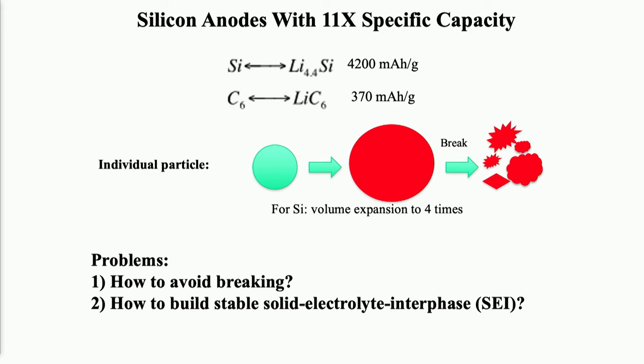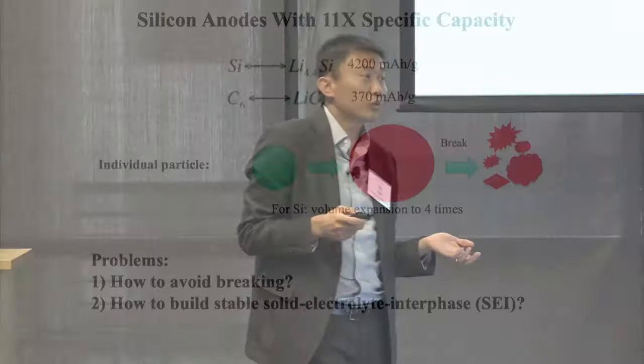Silicon stores a lot more lithium, but its volume expansion is gigantic. It's about four times once lithium is coming in. And it's going to break the silicon particles. It's going to make the surface, the interface of each of these particles with electrolyte not stable. So nobody knew how to solve this problem. I also didn't know how challenging this problem is, but I started anyway.